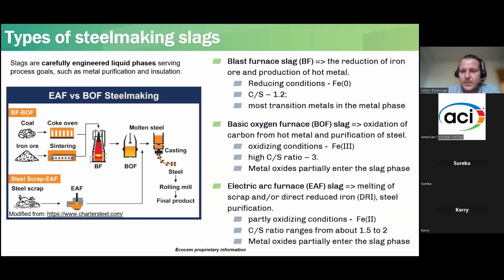And now we come to electric arc furnace slag, either from scrap metal recycling or from steel making from direct reduced iron. The oxidation conditions are somewhat intermediate. We find mainly iron 2 in the slags. We have also intermediate calcium-silicon ratios of about 1.5 to 2, and metal oxides partially enter the slag phase. So we have to deal with that as well.